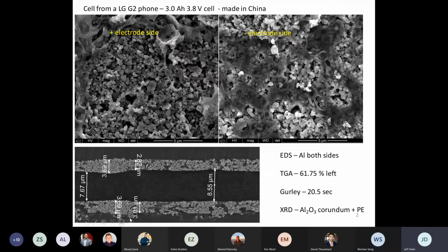No, the transition metals can penetrate through this separator because the electrolyte is going everywhere. So as long as the pores in the separators are not closed, the electrolyte can travel nicely. The ions in the electrolyte can travel nicely through here. The electrolyte is everywhere inside. But once the polymer shuts down, nothing can pass from one side to the other anymore.